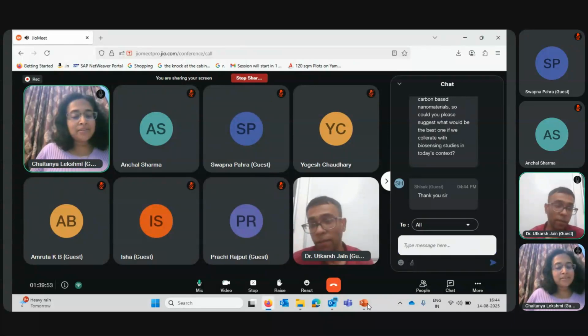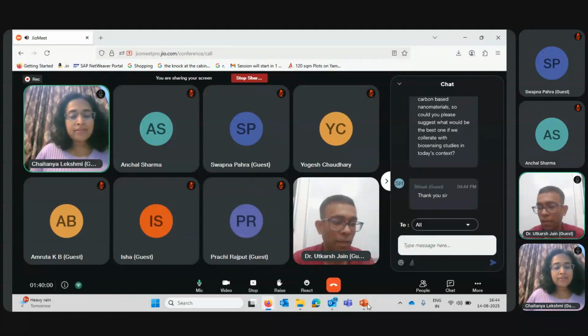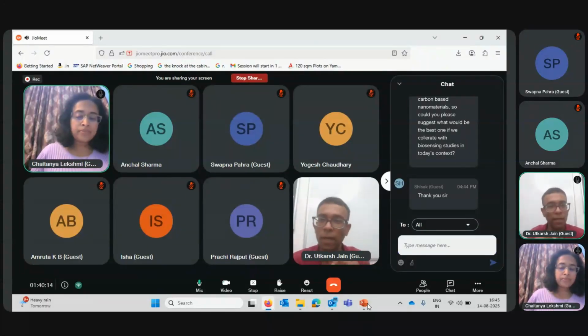First of all, why I have said that dropcasting is not a really accurate approach: in an enzyme-based biosensor, when you immobilize the enzyme on the electrode surface and load the sample on the enzyme-loaded electrode surface, the enzyme gets diluted and can be removed easily, because you drop cast and dry it.